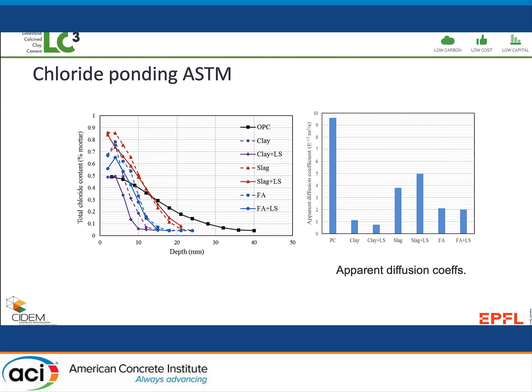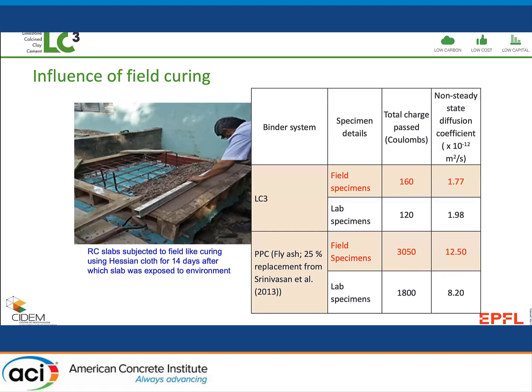So, don't get this idea that we're forming a very, very different microstructure. It's really the same microstructure, but this slowing down of chloride transport is due to interaction with the surface of the clay. And because the materials are much more fast reacting, it's much easier to get this improvement in performance in the field. So these are resistivity tests.